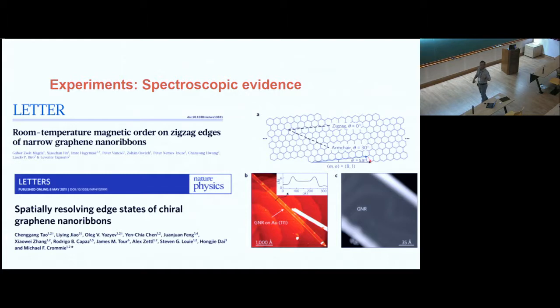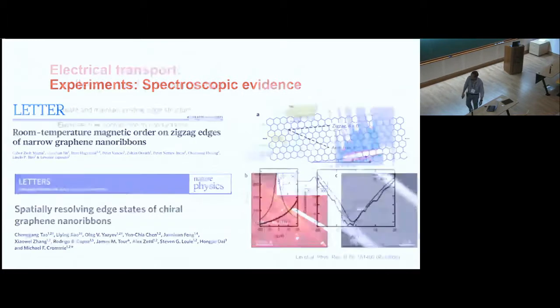In order to do so, most people try to open a quantum confinement gap. And hence, the best way to do this will be using carbon nanotubes, for example. That's what they started with. This is not a transport experiment, but using scanning tunneling microscopy, they looked at the states along the edges. And as you can see, this is a beautiful image where the scanning tunneling microscopy shows that there is a larger state available here than in the bulk. This is a graphene nanoribbon experiment, and this experiment came about 2 years ago.